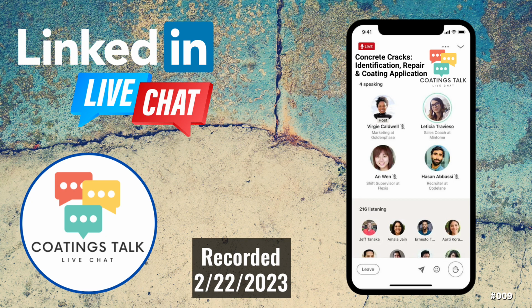And since the carbonation rate is a function of diffusion, the depth of the carbonation adjacent to a crack can sometimes provide an indicator of when the crack formed. This type of carbonation I'll probably mention a little bit later here in the conversation this evening. Now, cracks due to expansive reactions. Carbonation can cause cracking in concrete by contributing to the corrosion of the steel reinforcement. The high alkalinity of the concrete helps to prevent the rebar from corroding by formation of a passive layer